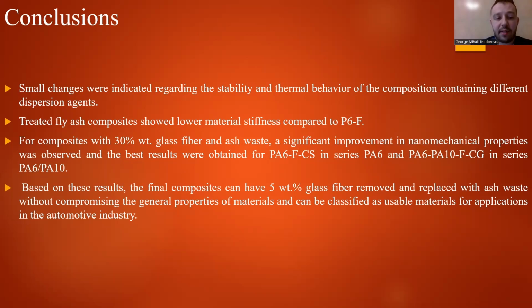The high flexibility without decreasing the stiffness by more than 20% in the composites with 5% ash and 25% glass fiber recommends these composites as an alternative to the composite with 30% glass fiber as usable materials for applications in industries such as the automotive industry.